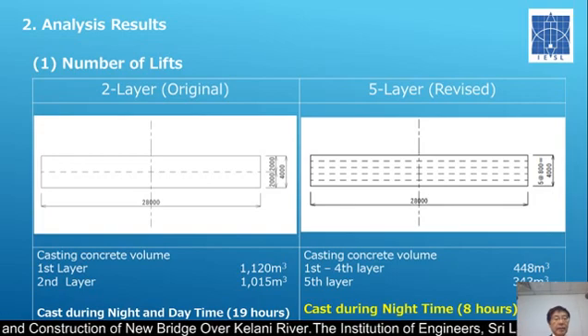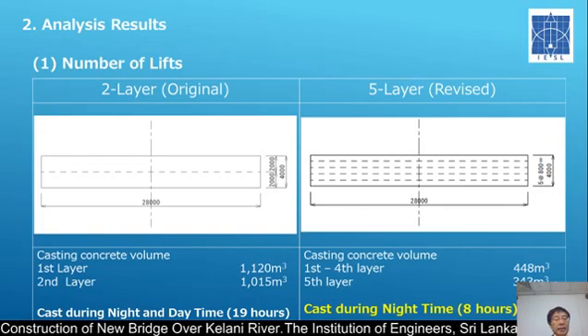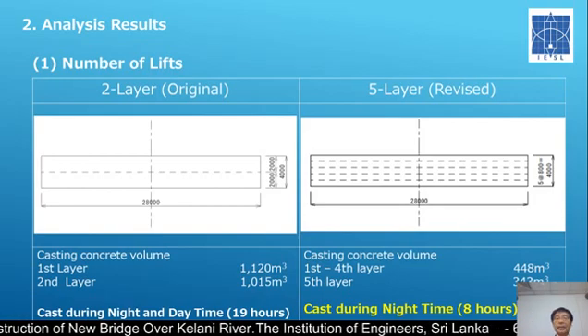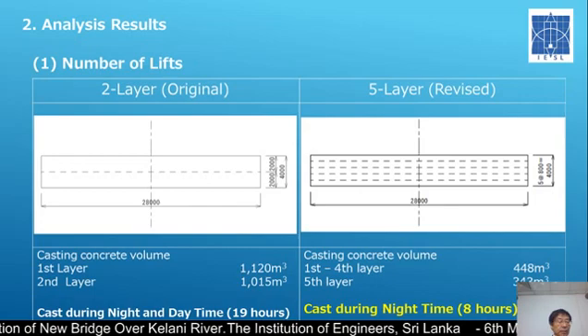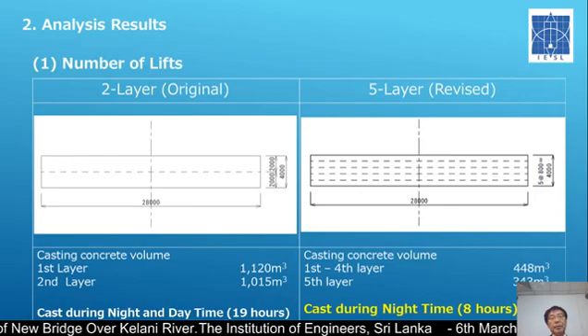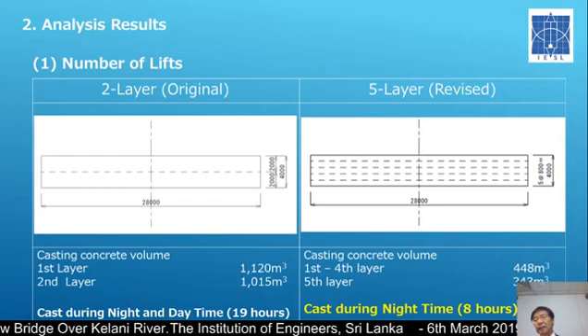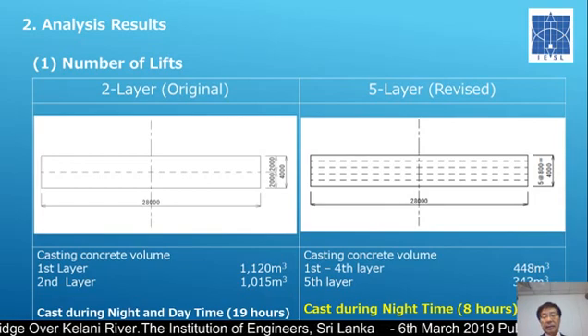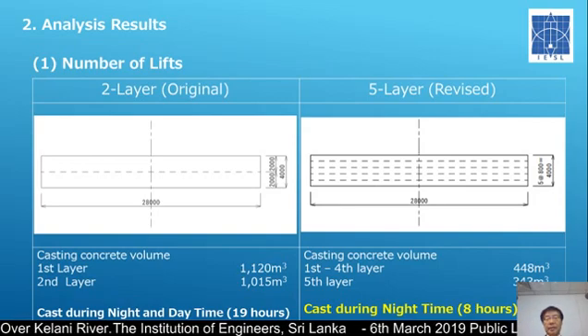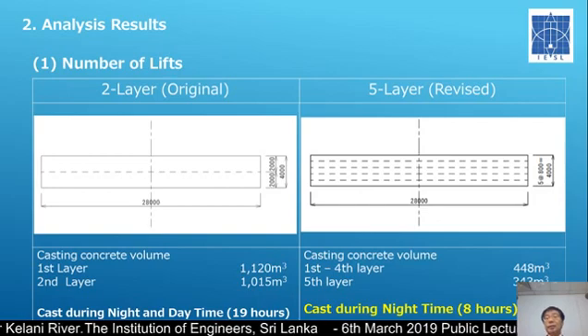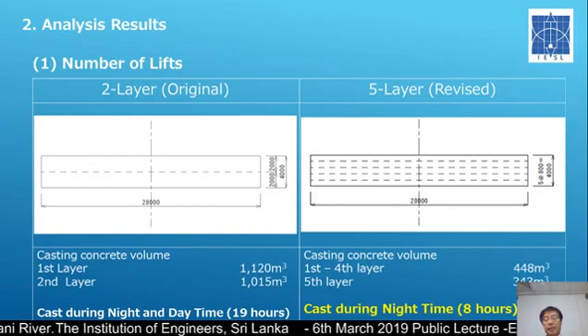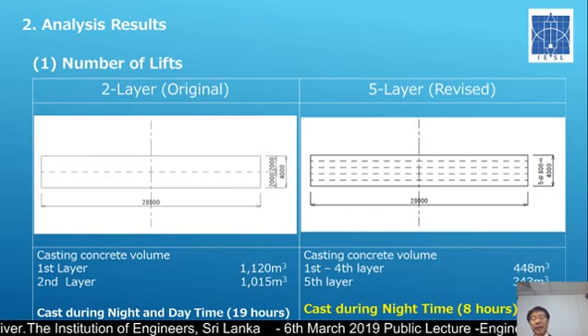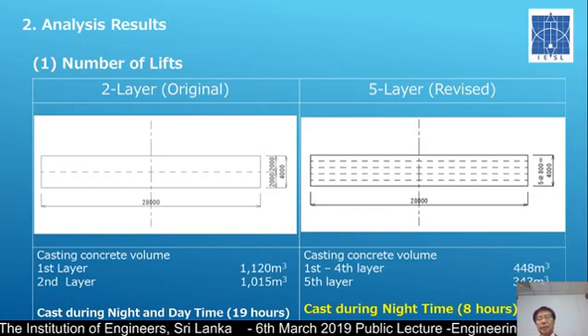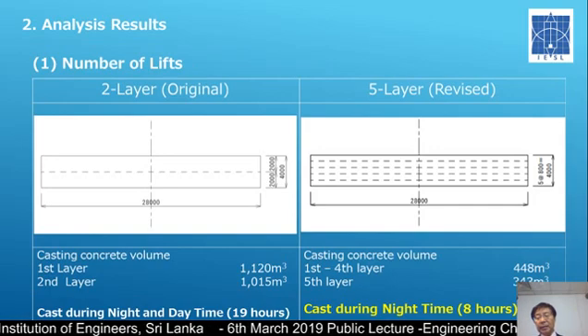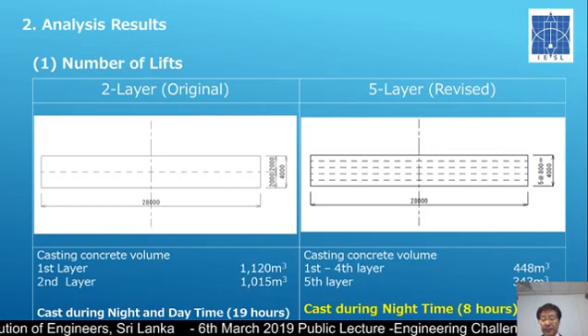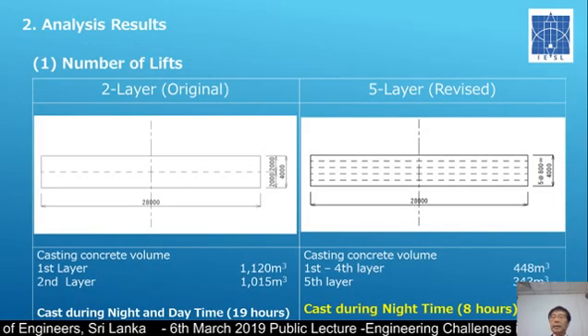The important thing that we want to stress is that in the case of the left hand side, 2 layer casting, the casting is to be done not only at night time but also in the daytime. That means the concrete temperature is going to be raised during the casting. But because lowering the casting temperature is most important, we consider that it is better to cast the concrete only at night time, which means within 8 hours. So we reduce the amount of concrete to be cast all at once, to about 400 cubic meters. So these 2 comparisons are theoretically done.